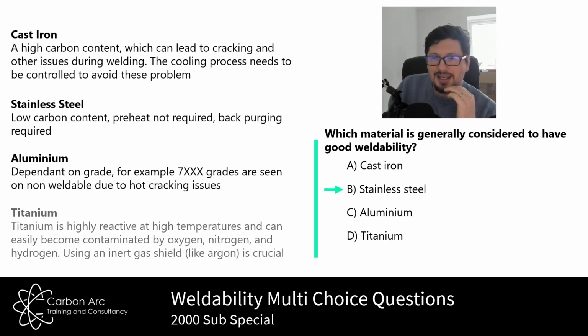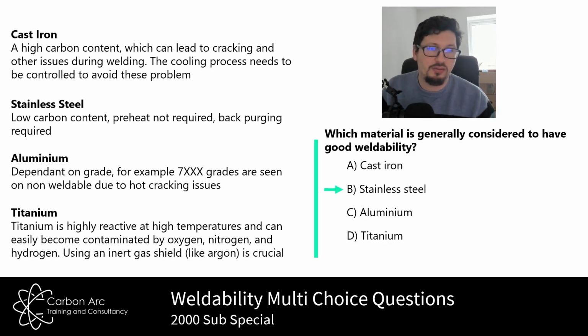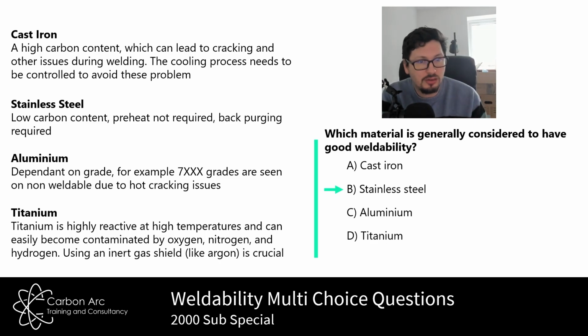And here on the list, we've got just some examples of the different things that I've talked about there. So cast iron, poor weldability, high carbon content. Stainless steel doesn't need preheating because it has a very, very low carbon content, especially if it's a 316L or something like that, low carbon grades of stainless steels. Aluminium, some of them hot crack, 7000 grade doesn't weld, because it has hot cracking issues. Titanium, a lot of things around it to keep it clean, oxidization free and stuff like that, so that's relatively difficult. Okay.